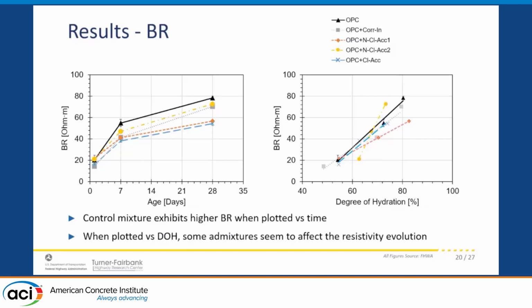And this kind of tells us that some admixtures might change the microstructure evolution over time, but in general, the ones that we observed did not really have a major effect on the microstructural evolution.